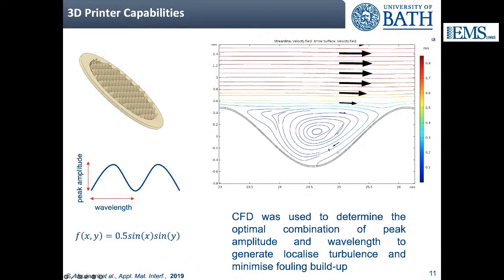And so this is a formation of turbulence that helps dislodge fouling from the surface of the membrane or to slow down its accumulation. And you can design this double sinusoidal structure with a simple equation shown at the bottom left of the slide by controlling two key parameters. One is the peak amplitude, which is the height of the peaks and troughs in the membrane, and the other is the wavelength, which is the distance between two peaks.